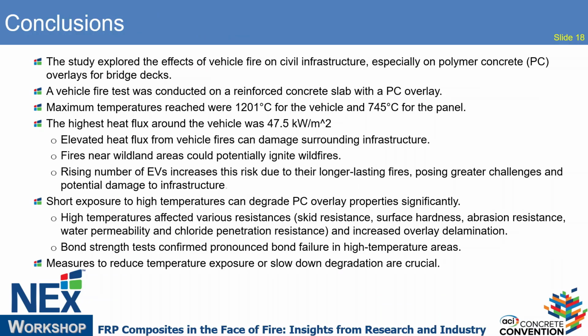So this is the conclusion for this study. Basically, this study explored the effects of vehicle fire on civil infrastructure, especially on the polymer concrete overlay for the bridge deck. We conducted a vehicle fire test on a reinforced concrete slab with the PC overlay. The maximum temperature reached was 1,201 degrees C for the vehicle, and this is a compartment fire inside the vehicle. Over the slab surface, the maximum temperature we measured was 745 degrees C, and the highest heat flux around the vehicle was 47.5 kilowatts per square meter.